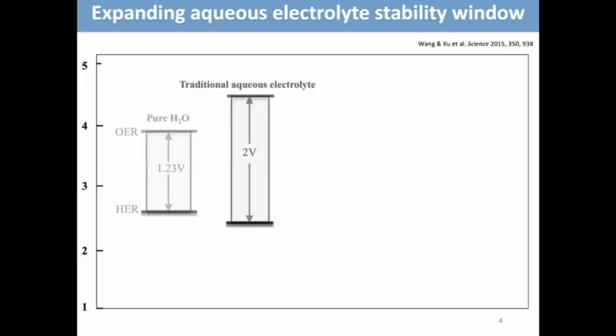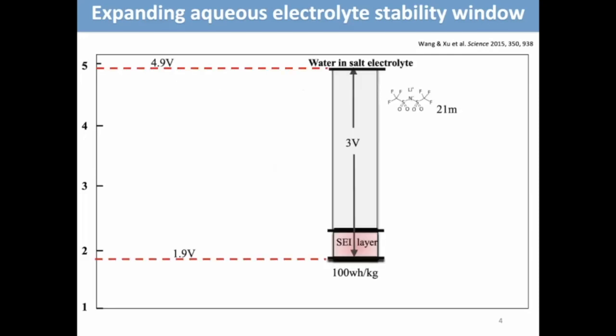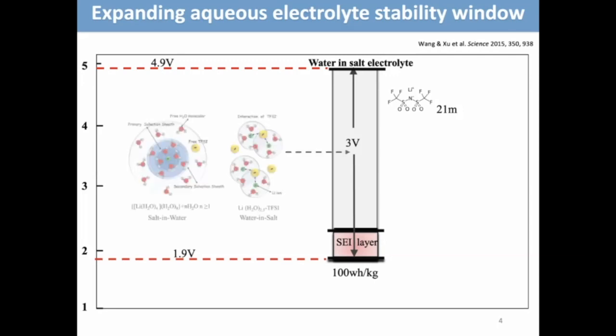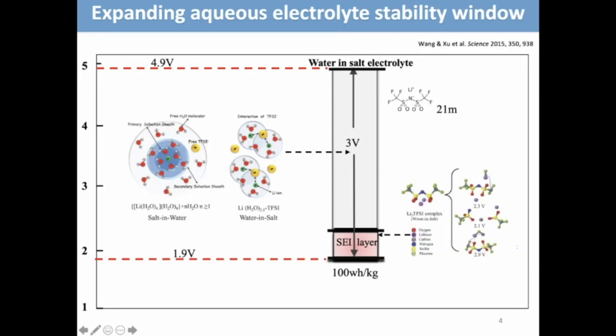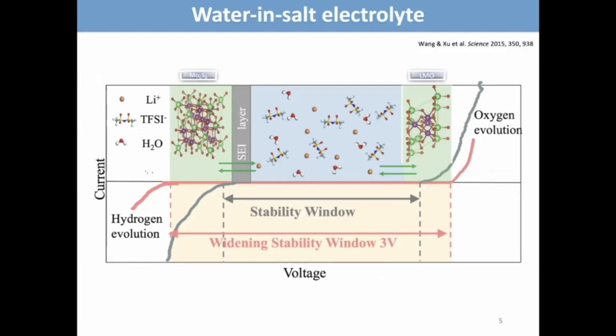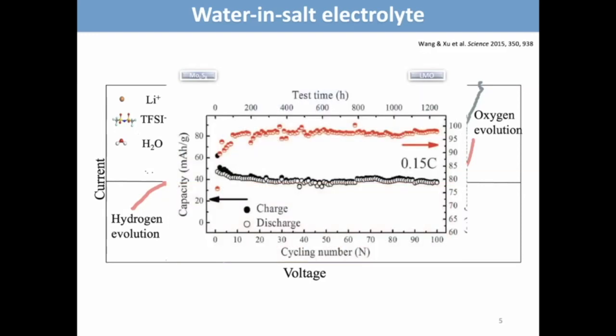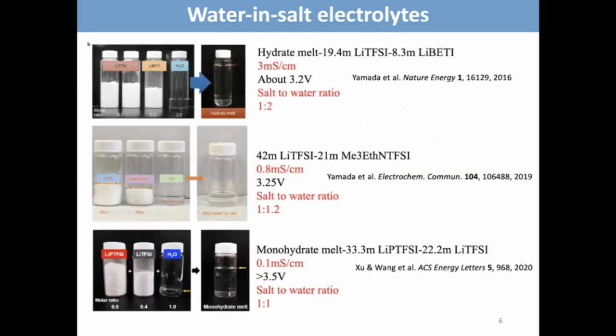However, water is limited by its stability window, and traditional aqueous batteries are limited to around 2 volts. Thanks to Professor Wang and Professor Xu's group, who proposed a new concept of water-in-salt electrolyte, using highly concentrated electrolyte to stabilize water by reducing free water molecules as well as forming a stable SEI layer. Their work has been widely applied, and they showed a working prototype of a full aqueous lithium-ion battery with more than 3 volts and very stable cycling stability as well.